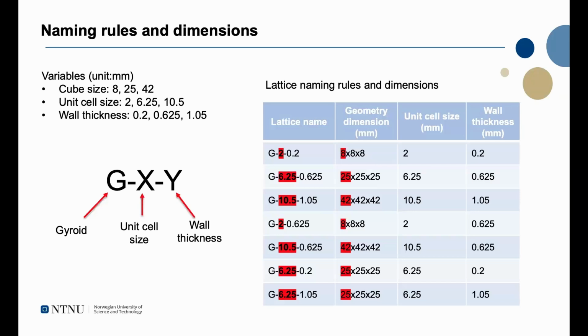There are some naming rules and dimensions for all the specimens. The cubic size we chose ranges from 8 millimeters to 42, corresponding to different unit cell sizes. We use the names where G stands for gyroid, X stands for unit cell size, and Y stands for wall thickness. So by looking at the name of the lattice structure, we know all the parameter details. These are all the detailed parameters, as we can see in the highlighted numbers here.